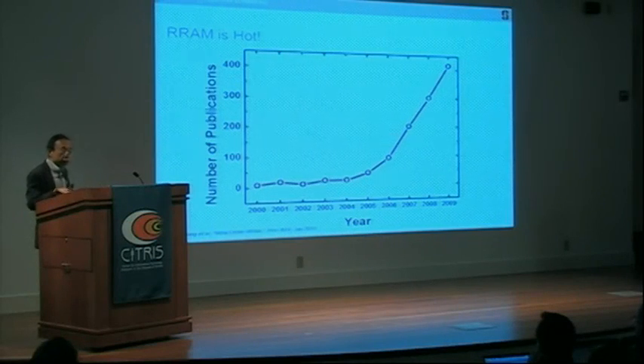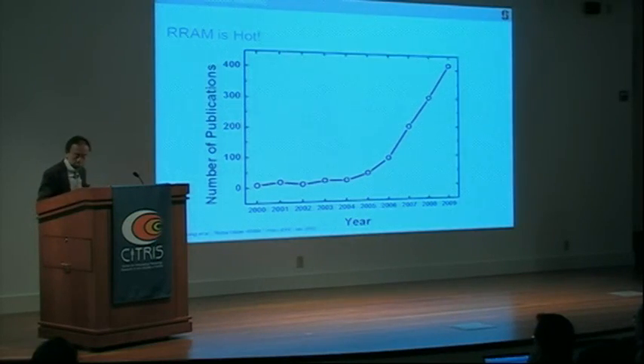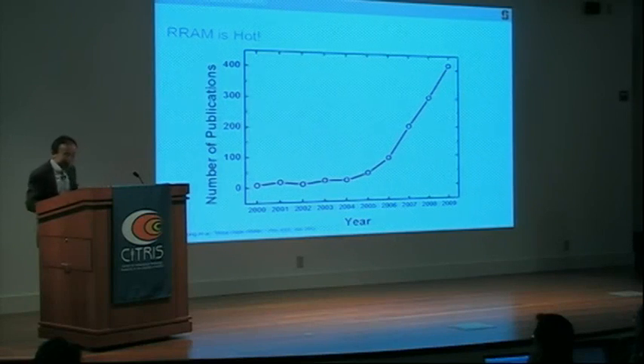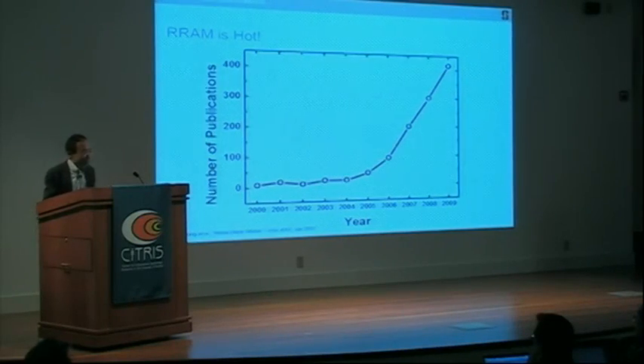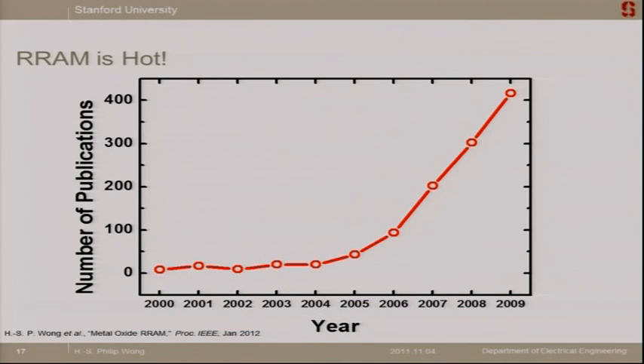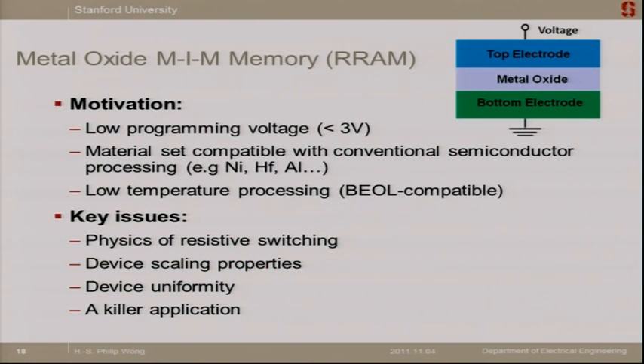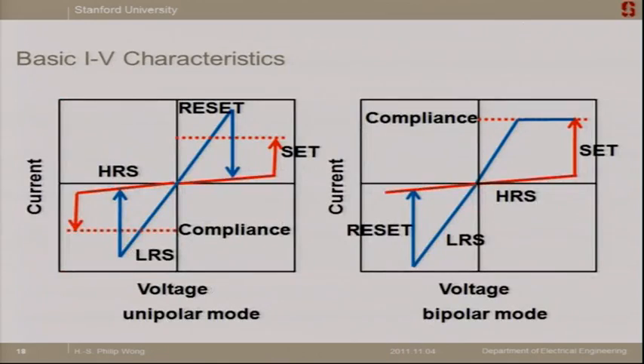Another device is the metal oxide RRAM. This one is even hotter than the phase change memory. You can see the number of publications explode in the past 5 years or so. What is RRAM? It is very simple: top electrode, bottom electrode, and sandwiched in between a metal oxide. And this metal oxide could be very simple, like hafnium oxide or aluminum oxide, the kinds of oxide that we're familiar with in the high-K literature. And the processing is low temperature compatible, so you can imagine building these on the back end of the line of a CMOS.